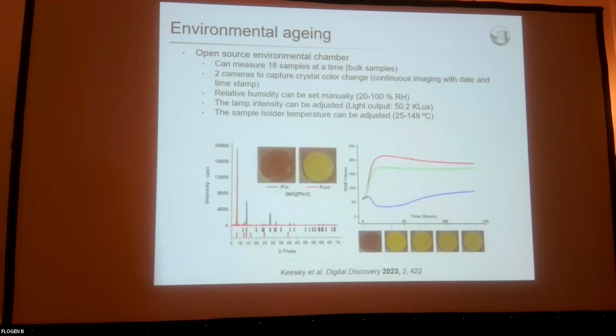When we look at this, and here are some data for methylammonium lead iodide, from the optical images for each of our different samples, we can extract RGB values, and they correlate to structural changes within our system, which we could measure using ex situ techniques. So this was all lead work, and we looked at a couple of different workflows. We looked at different halides, many different A-cations. We wanted to see if we could extend our robot-ready perovskite approach to other B-cations as well.